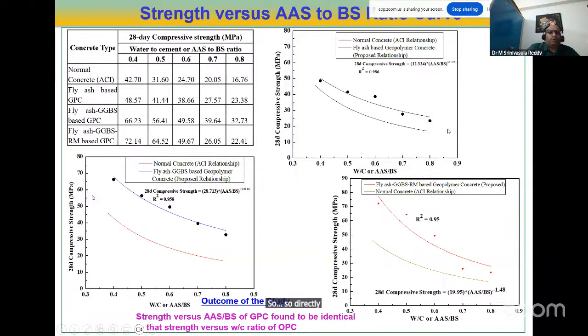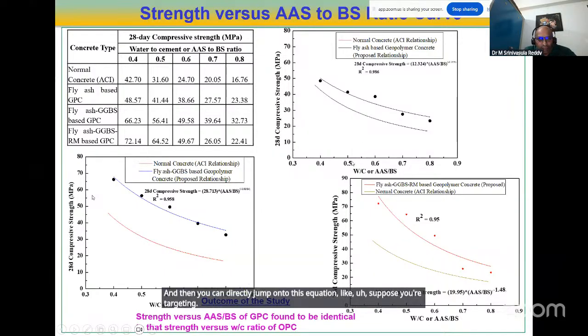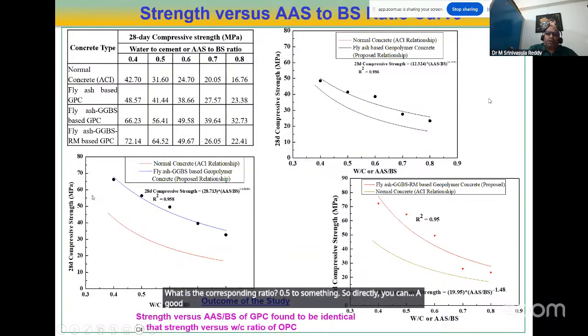So if you want to jump directly to mixing the concrete, you can directly follow this, if the properties of your binder solids are similar to what I have shown here. Suppose you are targeting 40 MPa. What is the corresponding ratio? It is 0.5-something. So directly you can start your mix proportioning by considering the AS to BS ratio as 0.52. You already know the ratio and AS, so you can find out the binder solids. You already know the specific gravity of the materials used. So within minutes you can calculate the composition of the various materials required for your targeted strength.